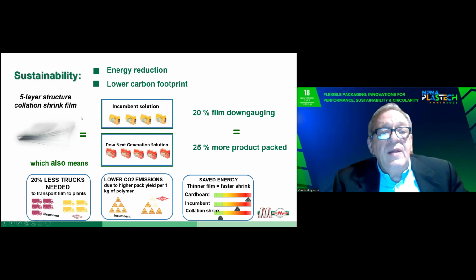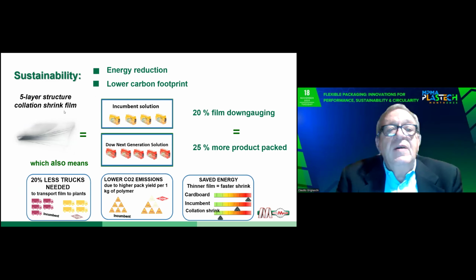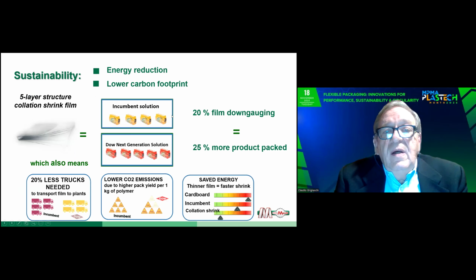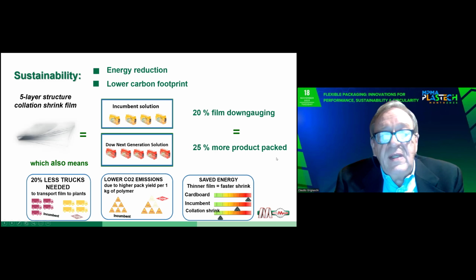Talking about sustainability—the example is based on collation shrink, as this was the first driver for this development. 20% film down gauging means 25% more product packed with the same quantity of resin, but also 20% fewer trucks needed to transport film to plants. It means lower CO2 emissions due to higher pack yield per kilogram of polymer, and once on the shrinking machine, you need much lower energy—thinner film means faster shrink at a lower temperature.